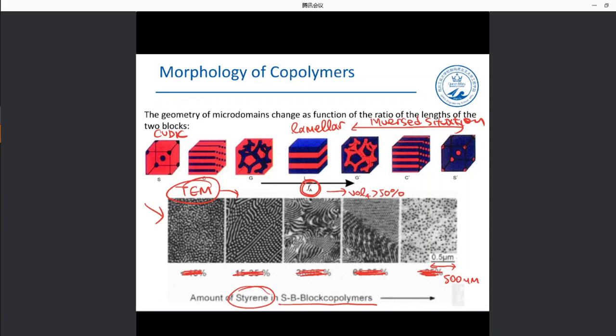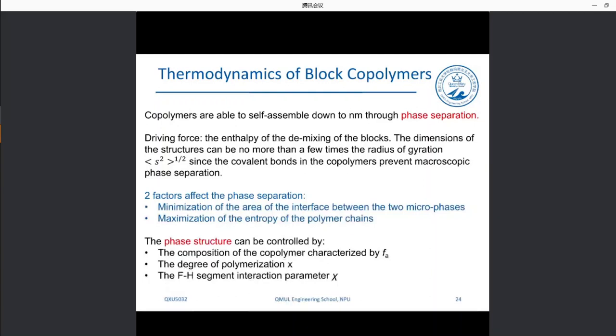So, as we said several times, the most interesting part of copolymers is that they're able to essentially phase separate, self-assemble on the nanometer scale into ordered structures through the process of phase separation. Okay, and thermodynamically, we say that the driving force in order to create that is the enthalpy of demixing of the blocks. That leads to a tendency for the blocks to phase separate in